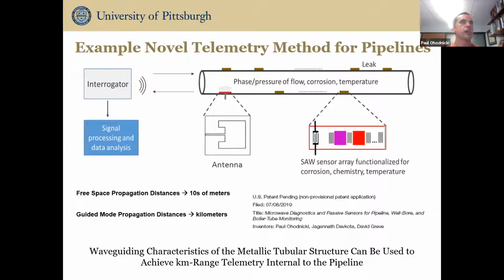This is one example, as I said, where you have a pipeline. You may have, it could be surface acoustic wave or other types of passive wireless devices. You can excite a propagating electromagnetic field. It takes on a guided mode within the structure because it's basically a metallic tubular structure. As it turns out, if you were to try and do interrogation in free space, you may range over tens of meters for typical frequencies relevant for passive wireless sensors.